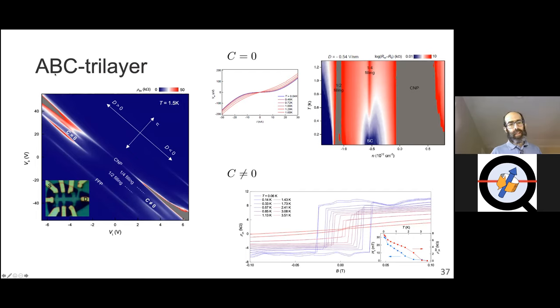And it turns out that it's important whether the third layer in the stack is sitting right on top of the first layer or offset from it. ABA would be where it's sitting on top and it's slightly more energetically favorable. ABC is offset. And so if we look at this ABC system, it's very rich.